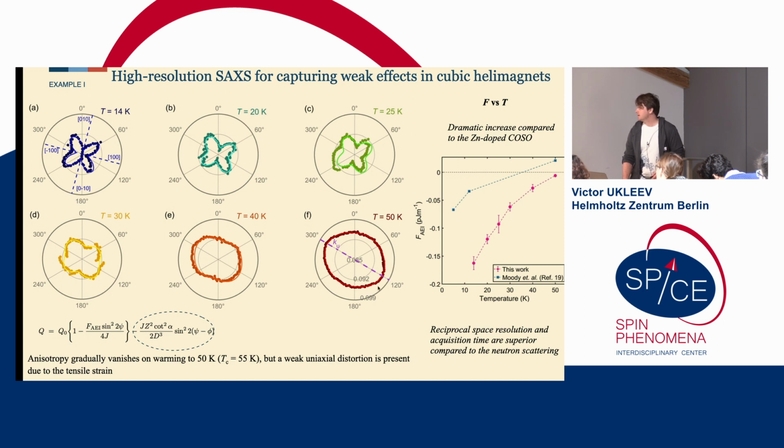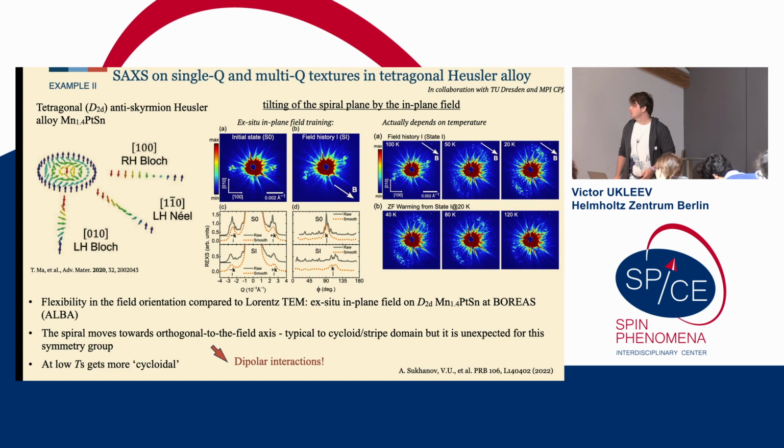Here we still have some uniaxial anisotropy, induced actually by the strain applied on our crystal. And by fitting this equation, we can easily obtain the temperature dependence of the anisotropic exchange, and we really see that it's enhanced towards lower temperatures. Therefore it's likely supporting the theory of Andrei Leonov about the competition between the exchange anisotropy and cubic anisotropy, because we see the exchange anisotropy really gets quite large at low temperatures.